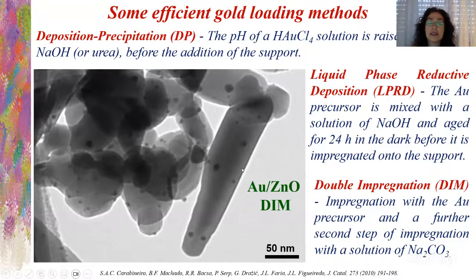So we have here an example of gold on zinc oxide prepared by this DIM method, in which we obtain small nanoparticles. The reason to use sodium hydroxide and sodium carbonate is that the sodium reacts with the chloride and forms sodium chloride, which is removed by washing. So we get rid of the chloride in the materials that causes the sintering.